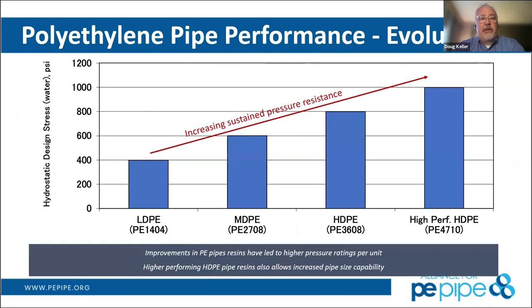Over the years, polyethylene has evolved, and this is a good thing. Polyethylene can adapt and can be changed to the current needs of the material. We start off with a PE 1404 material. If you have a lawn sprinkler system, or if you have installed one, that black pipe you can get at one of the big box hardware stores is a PE 1404 material. PE 2708 was the next evolution. This is what we call a medium density polyethylene. This would be yellow gas pipe. We then moved to high density polyethylene at PE 3608, and our current material for sale in the market on high density is a PE 4710 material. Over time, we've been able to increase the pressure handling capability of the material to adjust and to meet different market needs. Next slide, please.